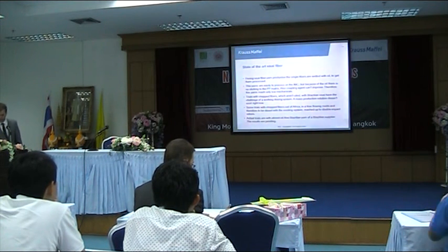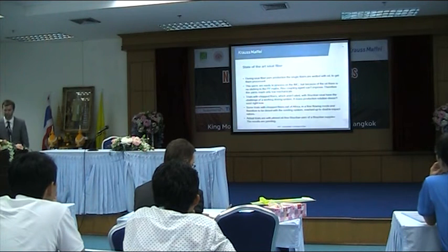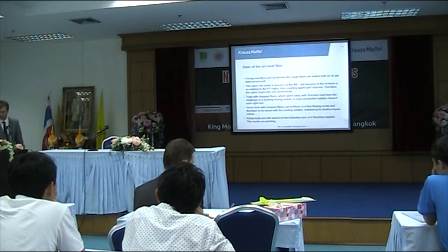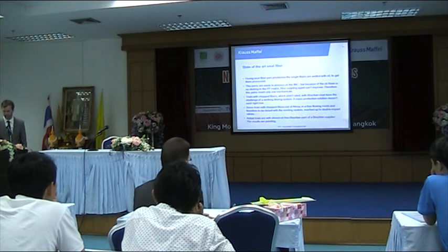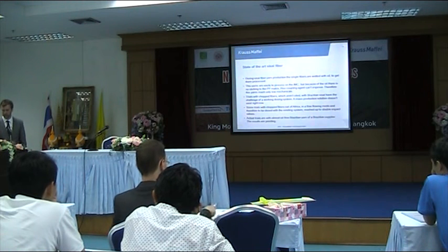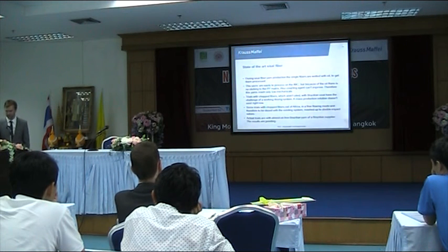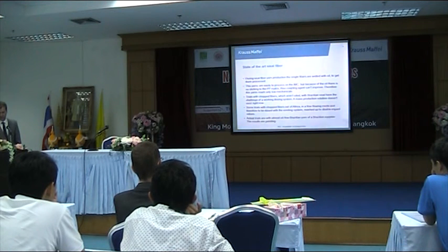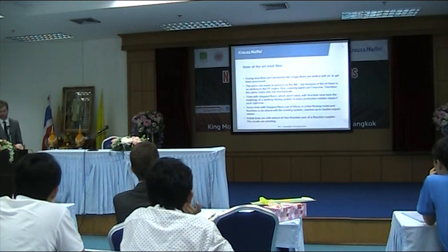Because of the oil, there is no sticking to the polypropylene matrix. Maybe the fiber experts will have more details on this. And so a coupling agent cannot improve it, and therefore these yarns, for example, reach only very low mechanical properties.